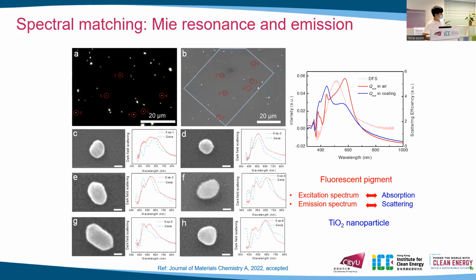So in the coating, the actual scattering peak should be less than 500 nanometers. That's why BAM has a higher Purcell factor, because it also has the emission peak lower than 500 nanometers, and it matches well with the resonance of TiO2 in the coating. Then we know that if we want to achieve a good Purcell enhancement, we should have some spectral matching.